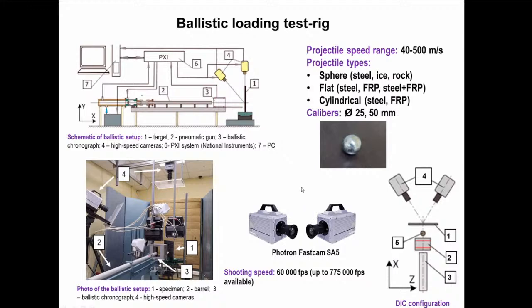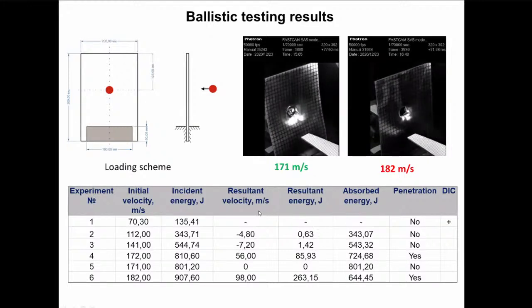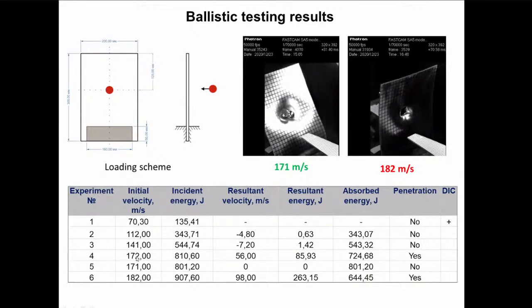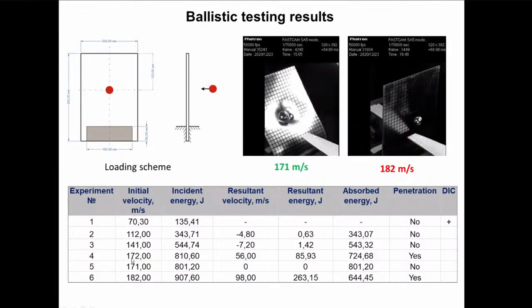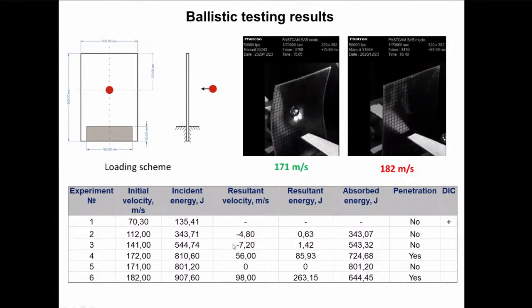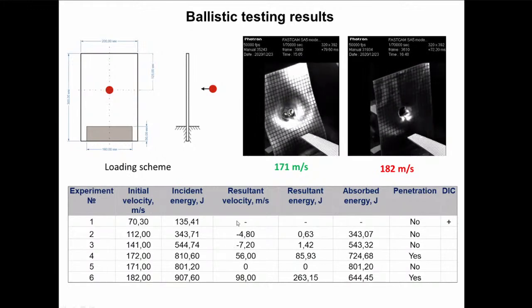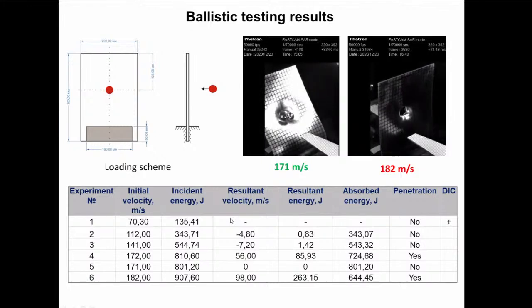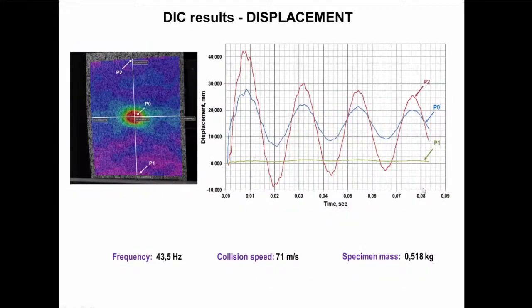In the second part of the study, we made the ballistic loading with our test rig, which allows us to obtain the kinematic characteristics of the specimen and of different types of projectiles, and also allows us to obtain the dynamic stress, strain and displacement fields using the DIC method, the digital image correlation method. The obtained ballistic limit was somewhere around 171 meters per second, and we hope that someone can use this data to fine-tune their mathematical models of the collision process of a rigid spherical projectile and this alloy.